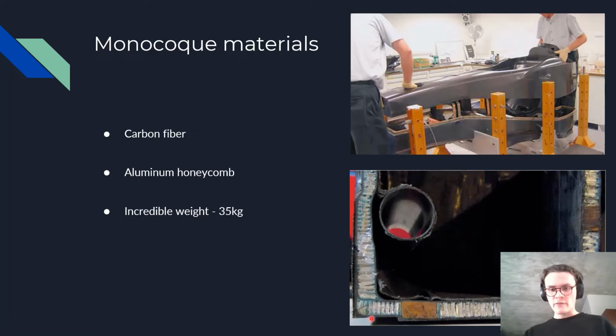So on the outside is about 10 layers of carbon fiber, about 1 millimeter. Then a thick layer of honeycomb is added, and then on the inside another 10 layers or so of carbon fiber. This is the most efficient way teams have found to make the monocoque as strong as possible while still being very light. And very light it really is, only 35 kilograms for the whole monocoque. It's a pretty large part, and it's super strong, as we'll see in a minute. So I'm really impressed every time by how light these things are.